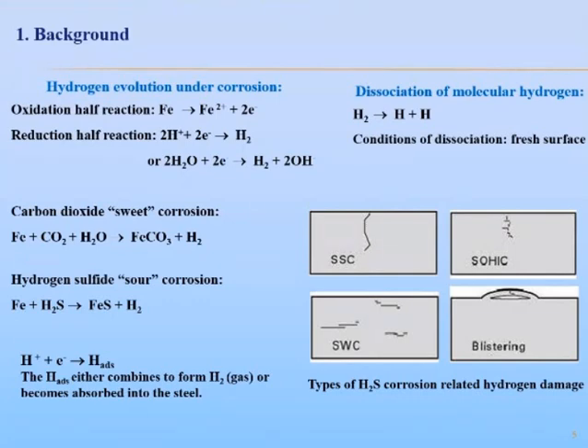Hydrogen can be available in the metal from various sources, including the electrochemical reduction of hydrogen, water, carbon dioxide, hydrogen sulfide, and other ions. Here you can see simplified electrochemical reactions for this hydrogen evolution. In the first stage, the formed hydrogen atom is adsorbed, and it either combines to form hydrogen gas or becomes absorbed into the steel. Here are also presented the most common types of hydrogen sulfide corrosion related to hydrogen damage.